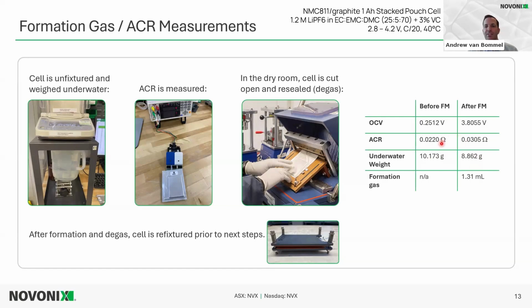We see ACR before and after formation. We can't 100% make this comparison because we are at a different SOC. The ACR when the cell is assembled isn't of like 100% use. But after formation, that ACR can be compared to different cells and may indicate different levels of SEI that are built up with different electrolytes, for example. And then the OCV before formation, after formation, is expected to be where we stopped it. It's a little bit